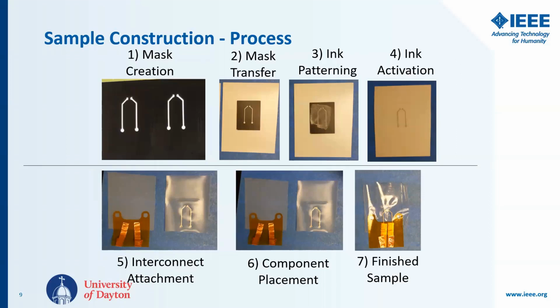The mask is removed, and then we place the interconnects onto our top encapsulation, place any electronic components that are going to be in the sample, and then press it in a heat press. Heated press at a pressure of 0.4 megapascals, temperature of 160 degrees Celsius for 120 seconds. Once this is finished, the sample is complete and ready for testing.